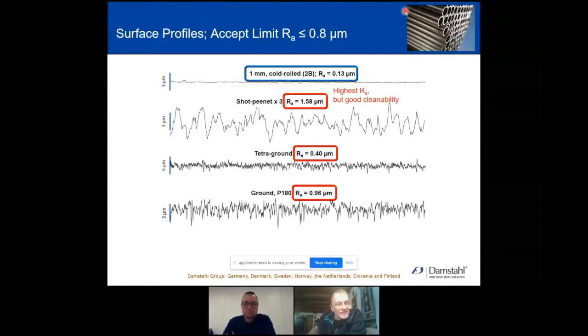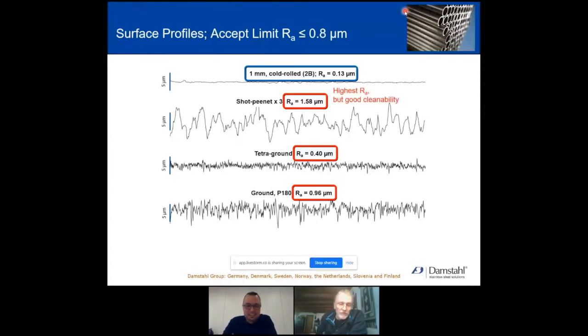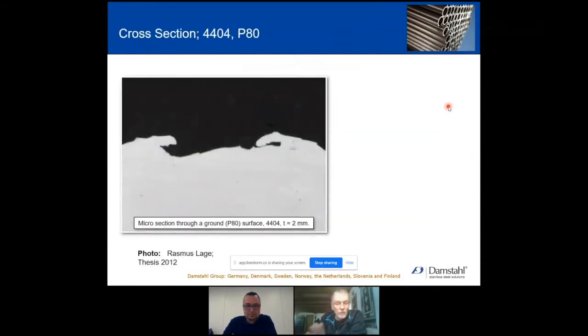So the shot peen one, you can say apart from the cold roll, is the best one of these four. But the shot peen is actually quite open, and it's very poor at holding on to bacteria and dirt and whatever, whereas the ground surface is actually no good. One of the reasons we see here, because this is actually a cross-section through grit 80, quite rough.